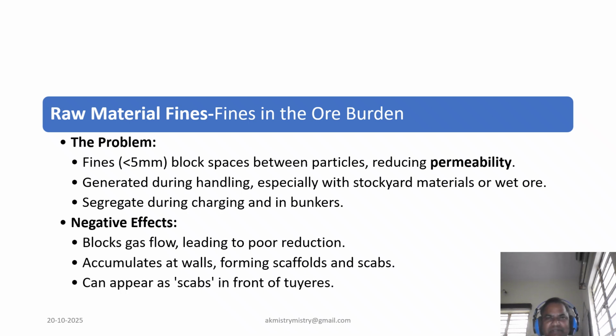The negative effects are severe. They block the flow of the reducing gases, leading to inefficient iron production. They accumulate on the furnace wall, forming destructive scaffolds and scabs. And in the worst cases, they can even appear as a solid scab right in front of the tuyere, threatening the entire process.